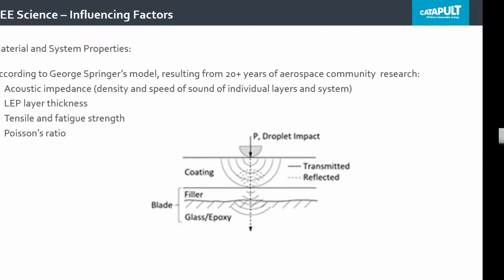This is because as the droplet impacts, it sends a shock wave through the LEP and then onto whatever is below it. Here I'm showing a classic rain erosion system, which is a coating followed by a filler or a glass epoxy. The filler could also be a gel coat. There could be a tape on top of the coating, or in new systems you could have a hard thermoplastic or metallic bonded onto the glass epoxy. There's a whole range. So you're sending the shock wave through the system until it hits an interface.